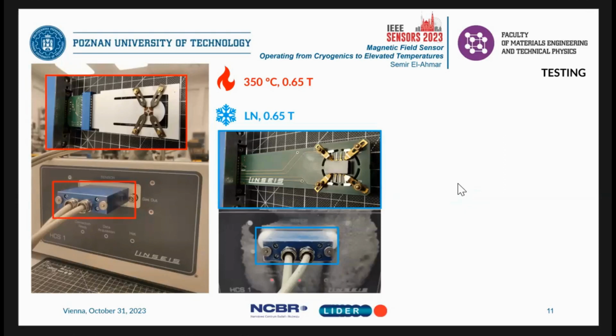And using this analyzer, we can create temperature conditions, not only at a high temperature level of a few hundred Celsius degrees, but also at a low temperature level, down to liquid nitrogen temperatures, using a magnetic field of almost 0.7 Tesla, which is quite nice.